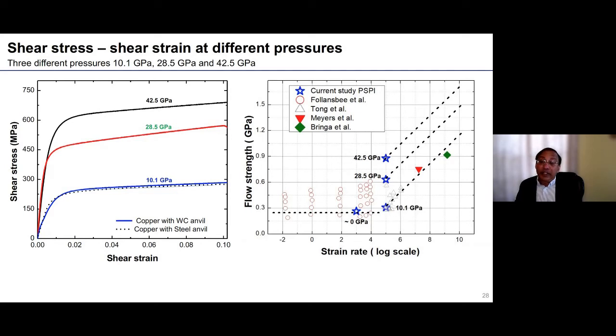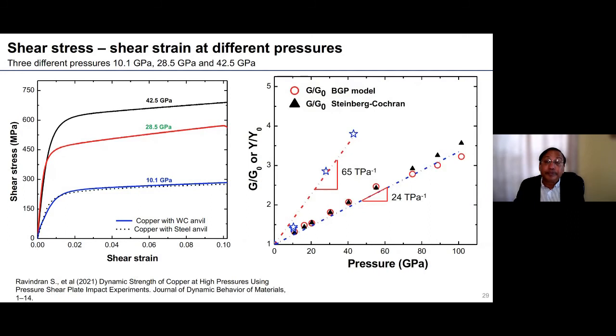As I mentioned, our strain rate is limited at this 10 to the power 5 per second because now the anvils are yielding. They are not remaining elastic anymore, and this kind of limits the strain rate which we can achieve. And this is something which we are again working on, how to achieve these higher strain rates.